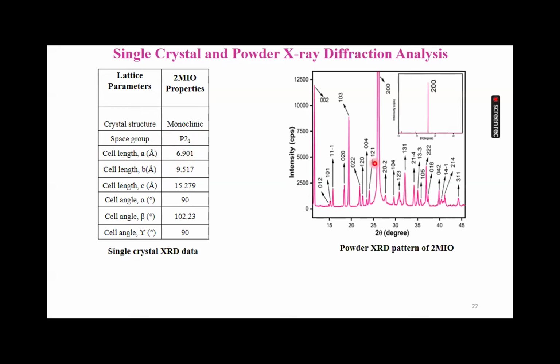The powder XRD analysis. The powder XRD of a sample can provide useful information about a sample such as phase identification, sample purity, hkl planes, and morphology. The broadening in the peaks of the XRD pattern arises due to the finite size of the crystal. If the crystals were of infinite size, the peaks in the XRD pattern would appear very sharp, and as the size gets reduced, the peak broadening increases.